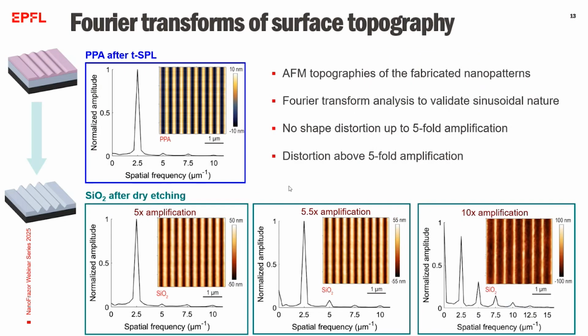Another important achievement is the quality of the transferred nanopattern. For this purpose, a Fourier transform of the measured AFM topographies is performed to characterize the sinusoidal nature of the fabricated nanopattern. And as you can see here, the polymer patterns are successfully amplified up to 5 times without any shape distortion. And this is further confirmed by the second harmonic component, which is only 3% of the main Fourier component.